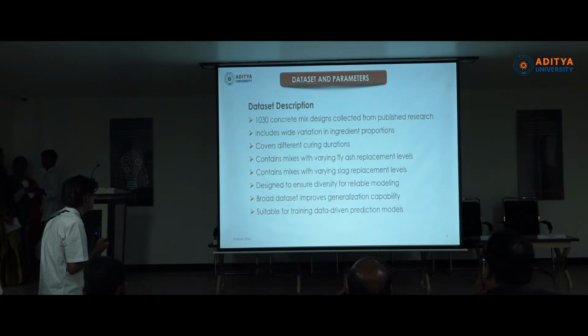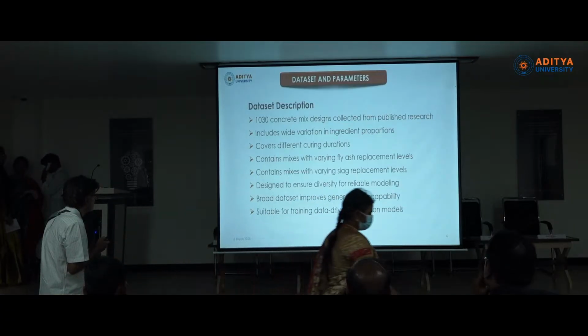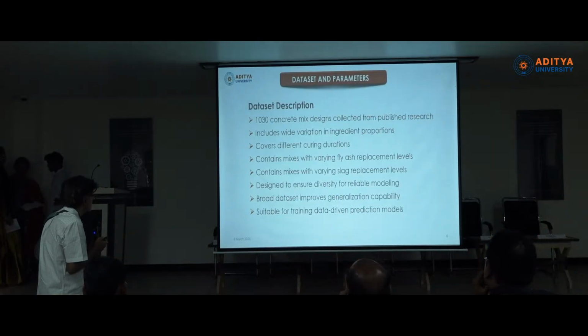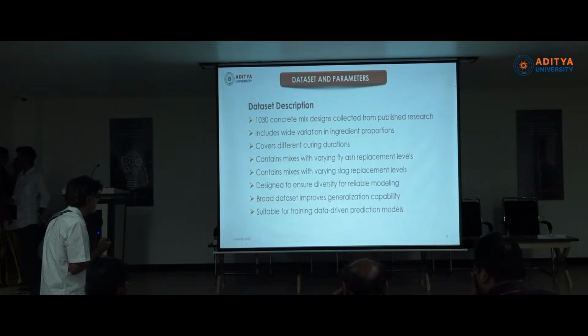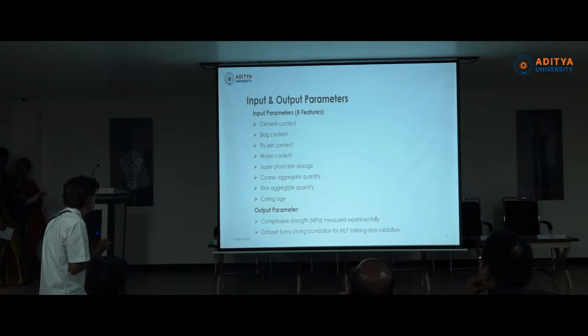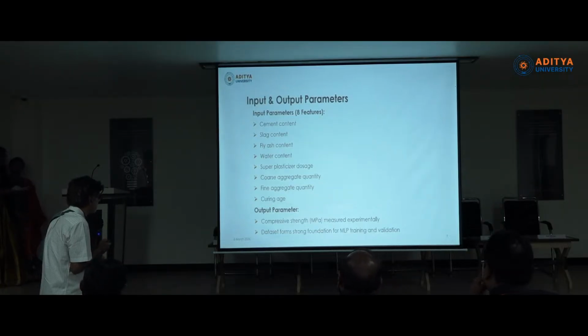Concrete mix designs collected from published research. Includes wide variation in ingredient proportions, covers different curing durations, contains mixes with varying fly ash replacement levels, contains mixes with varying slag replacement levels, designed to ensure diversity for reliable modeling. Input parameters: cement content, slag content, fly ash content, water content, superplasticizer dosage, coarse aggregate quantity, fine aggregate quantity, curing age. Output is compressive strength.